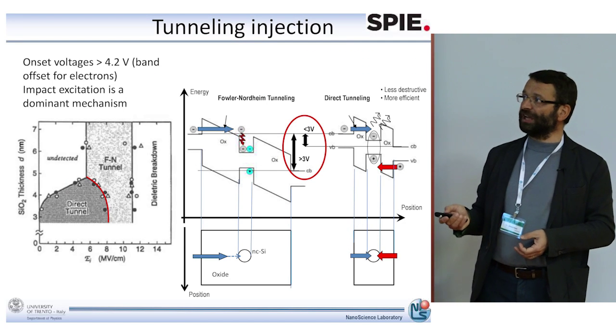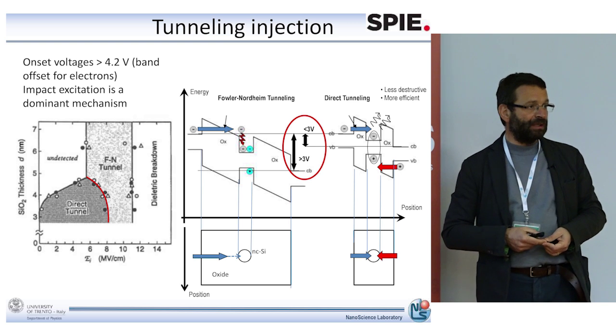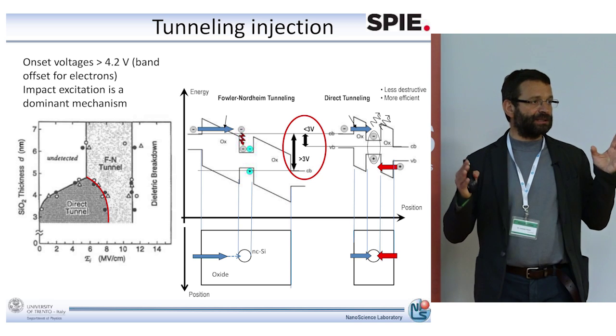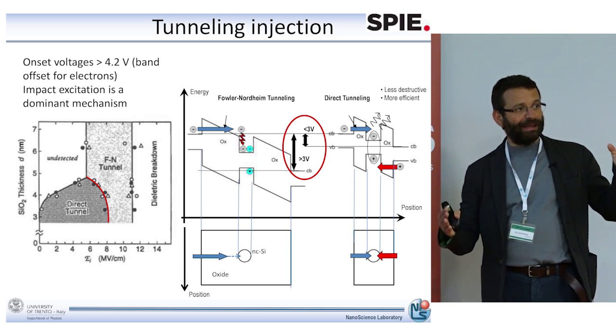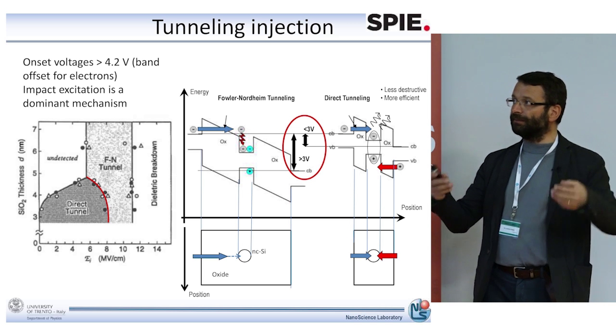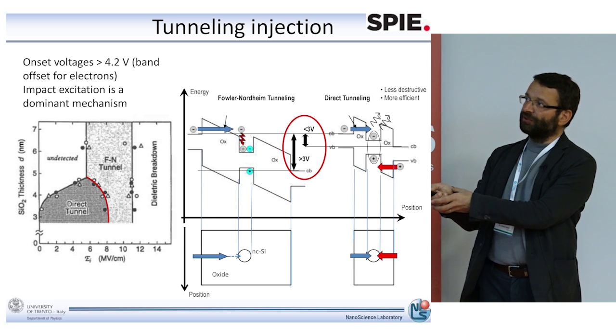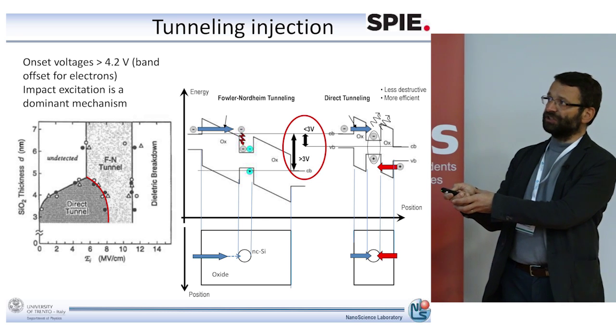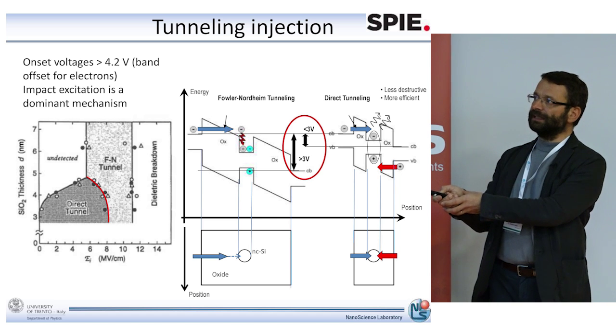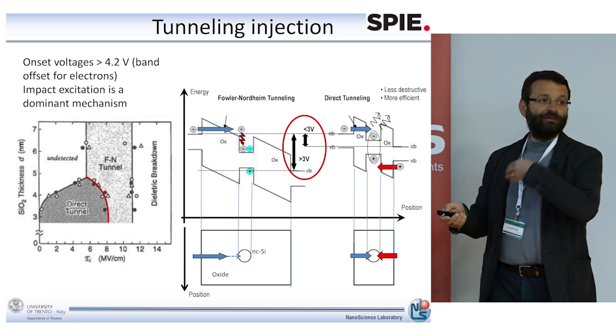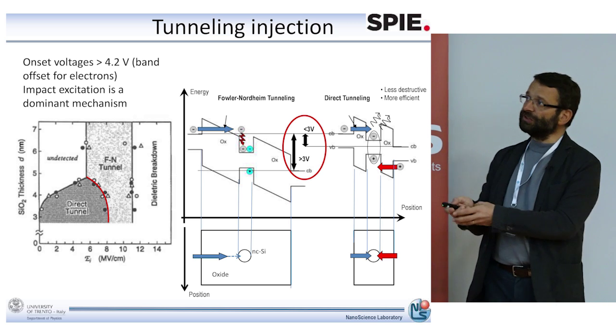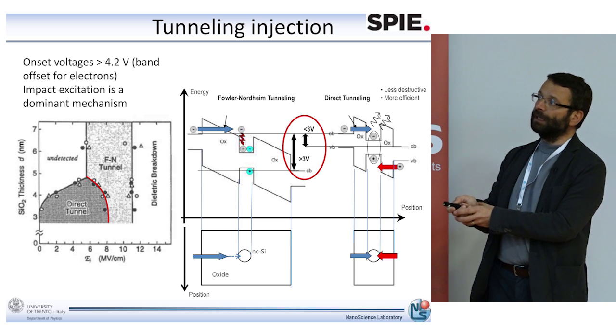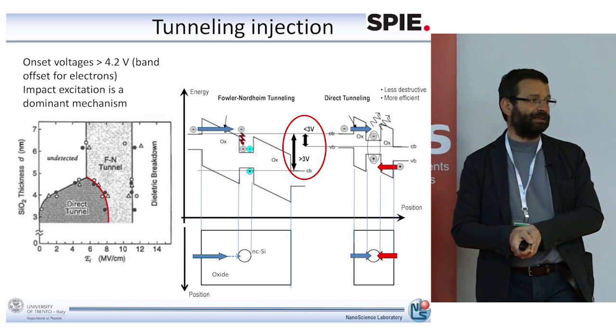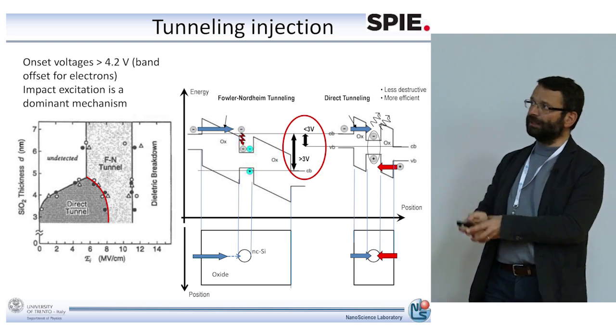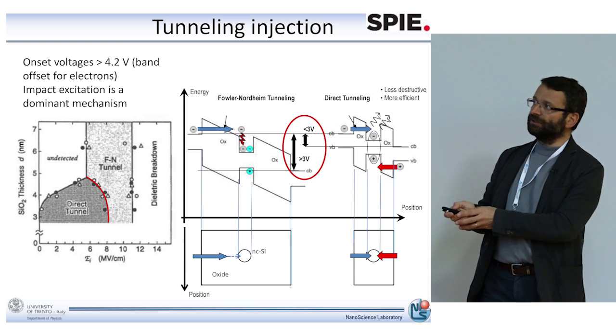If we want to use tunnel injection, what we have to do is go through the oxide. And here we have two possibilities. The first one is the case where we have a thick oxide: we apply an electric field, so we tilt the bands, and then we get an injection going through the oxide. We inject the carriers into the oxide, and then those energetic carriers impact the nanocrystal, and by impact excitation they excite electron-hole pairs from which we get the emission of a photon. This first approach is called Fowler-Nordheim tunneling, and the excitation mechanism is called impact excitation.